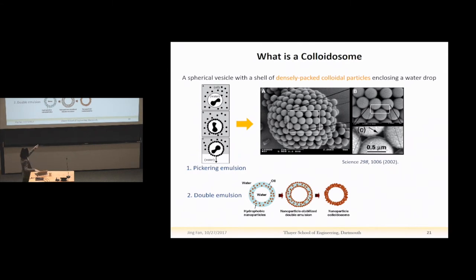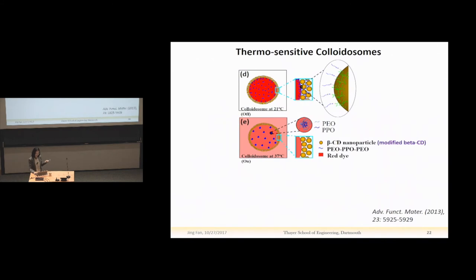But we can see that because of the interstitial pores among these particles, colloidosomes are intrinsically leaky, right? So this limits their application as a delivery carrier, especially to deliver small molecules. Then the molecules may just diffuse through the shell, which is not good. Right? So to address this problem, we propose the system as this.